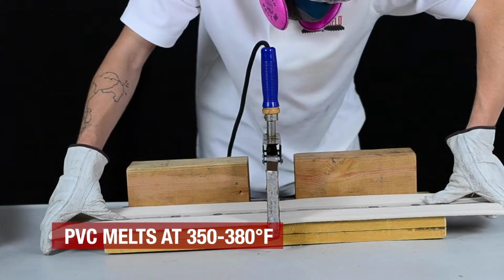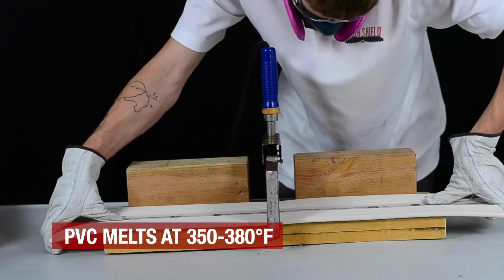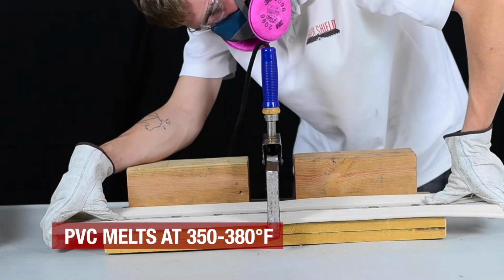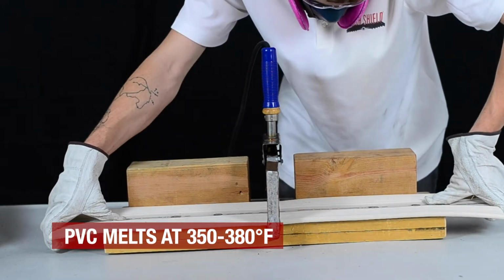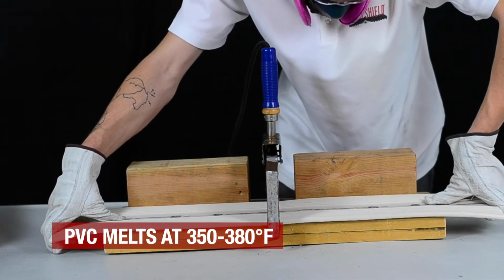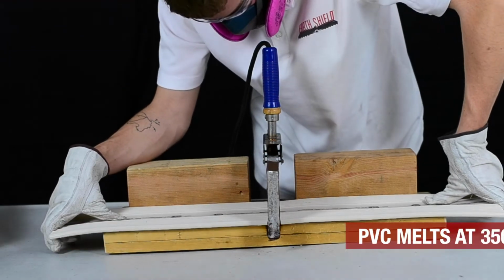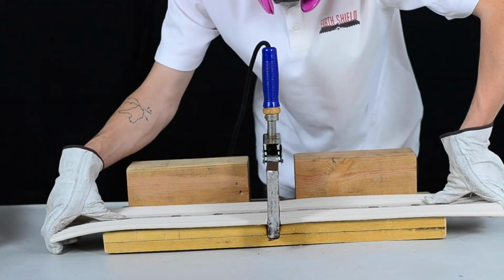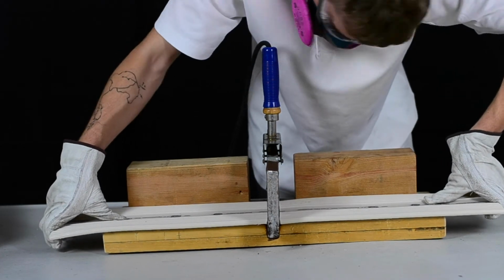PVC melts anywhere between 350 and 380 degrees Fahrenheit. If welded too hot, PVC will release its plasticizers, creating a brittle surface which will contaminate your weld. For the purpose of this video, the clips you're seeing are heavily sped up.